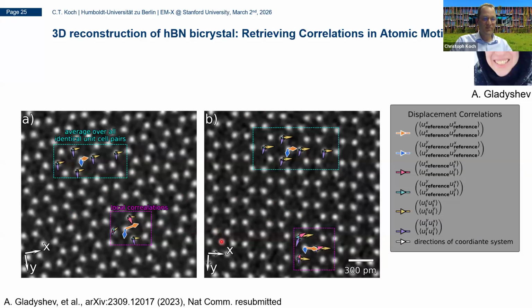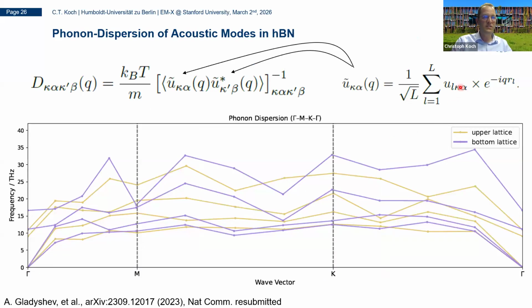We can now extract correlations, and these correlations between atoms we can then put into the dynamic matrix, and then invert this or find the eigenvalues and eigenvectors of it, and extract from that then the dispersion curve. So this is the same as what I showed you, this image by David Muller, which he has put into these MD calculations, which then produced this STEM image with the thermal diffuse scattering. And now this goes the other way around, taking basically this diffraction pattern information and extracting now the dynamic matrix, and from that also the eigenmodes and eigenvalues. And they correspond almost to the ones that we expect for hBN, hexagonal boron nitride, but they're a bit lower. And the reason for that is that we don't have full Z resolution yet. We only have about 1 nanometer resolution along the Z direction.